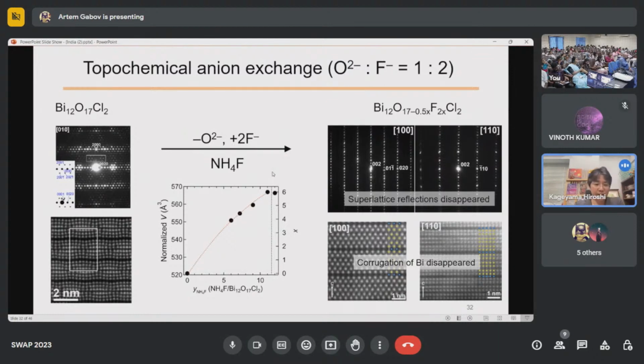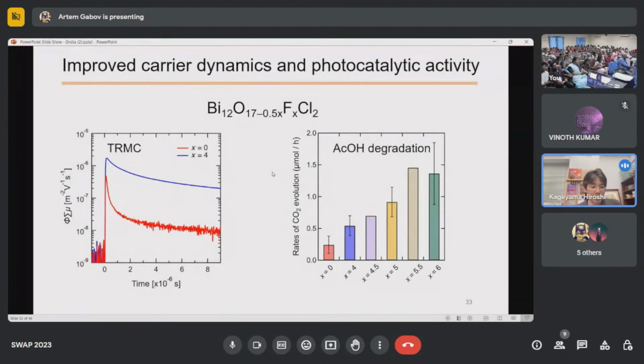But anyway, after this treatment, we observed that the modulated or corrugated block becomes completely flat. And luckily enough, we obtained enhanced carrier dynamics. Actually, by doping or exchanging fluorine, we are able to see the improved carrier dynamics and also catalytic performance. This is some organic molecule degradation test, and we observed that for the fluorine exchanged sample, the catalytic activity is significantly enhanced. Okay, so we are very happy about this.